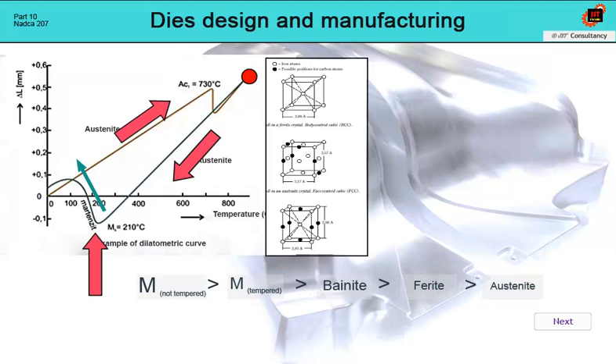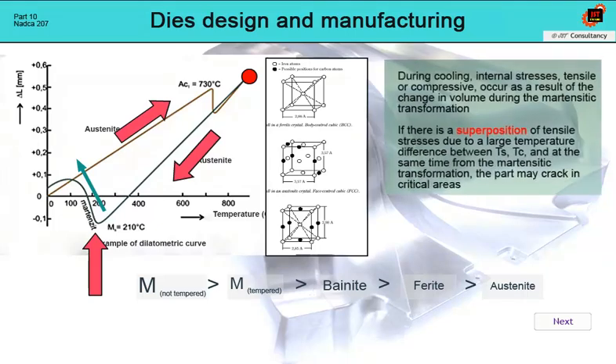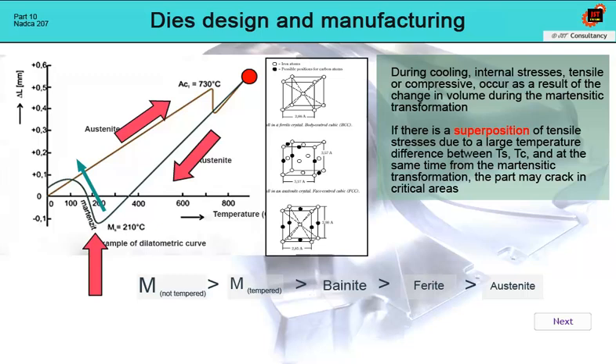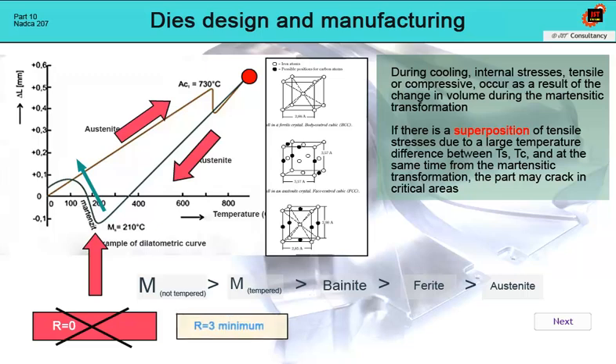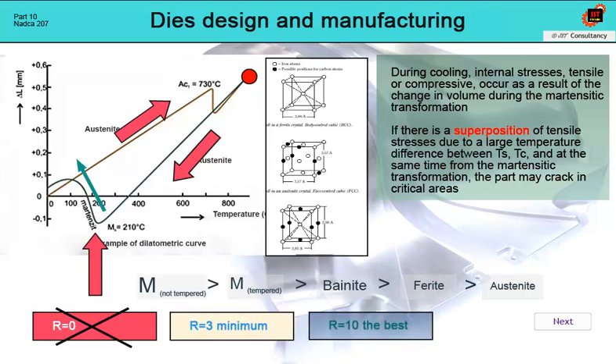If there is a superposition of stress from the temperature difference and from the martensitic transformation below the martensite start line, and at the same time it is in the area of tensile stress, there is a risk of cracking of the part. However, because due to the structure requirement, cooling must not stop at the martensite start line, we must deal with this problem primarily by ensuring that the shapes of the die will provide as few areas with potential concentration of tensile stresses as possible. This is mainly solved by sufficient radii. The radius R0 is practically inadmissible, the radius R3 is minimal, and the radius R10 means the safety of hardening.